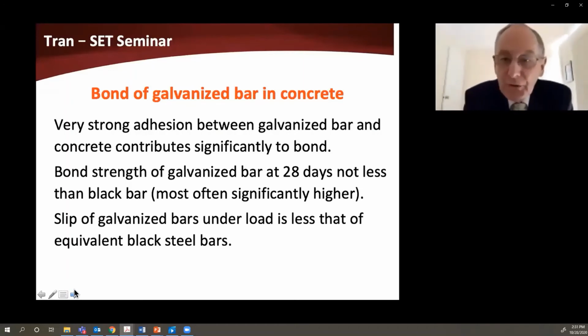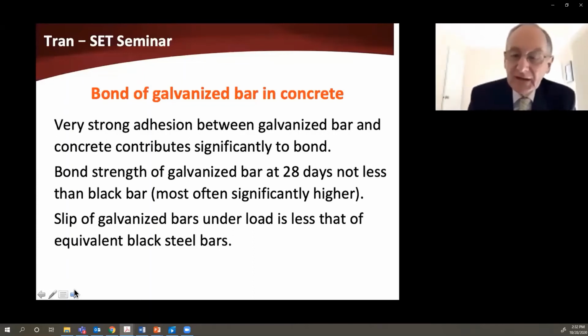There's a little bit of a cautionary note here, though. If you measure the pull-out strength of a galvanized bar in concrete at 7 days or 14 days, you may find that it is below that of equivalent black steel at the same time. This is because zinc oxide, which does come off the surface when the concrete is freshly exposed to the zinc, is an inhibitor. It does slow down the hardening of the concrete. But by about 14 to 28 days, when the concrete is well and truly hardened, that process has completely stopped, and then the bond of galvanized bars is generally significantly higher than that of equivalent black steel. So there's no question about change in the bond.